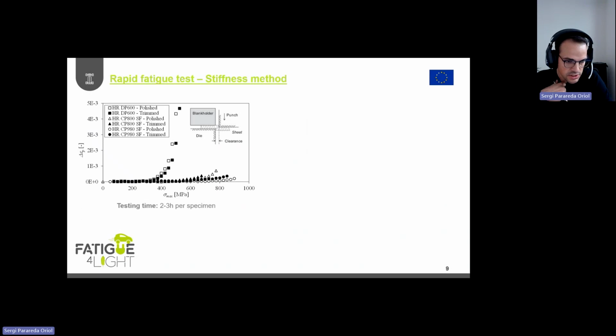So here you can see some results that we obtained for these 3 materials, and also the results for different edge conditions. When we talk about different edge conditions, we mean that we have hourglass specimens, for instance, and we polish the edges. So this is the polished condition. But then we also included the trimmed condition. So we mechanically sheared the edges, and we obtained the well-known edge shape where we have different defects and so on. And we tested all of these different conditions for the different materials. The good point is that we can obtain the results in 2-3 hours per specimen.